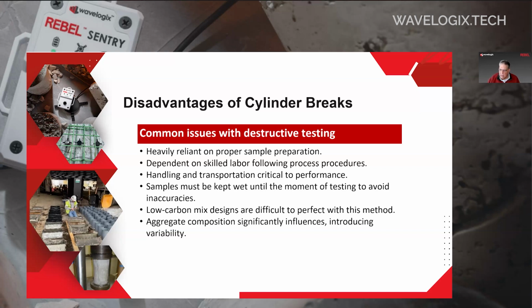On top of that, that cylinder typically has to stay at the site for about 24 hours until it gets hard enough to transport it. If you transport it before it's hardened properly, the jiggling around and bouncing around in a transport vehicle, your car off of a job site or truck, that could cause problems in the cylinder not coming up to full spec.